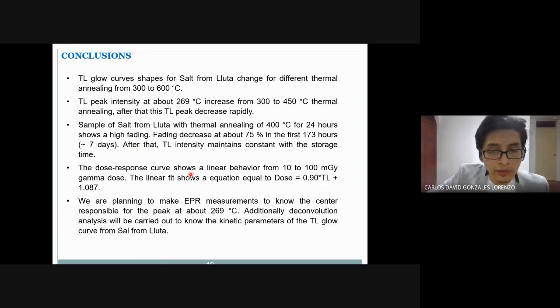The dose response curve shows a linear behavior in this range of gamma dose. The linear fit corresponds to this equation, as you can see here. However, more radiation dose will be necessary to know up to what point the linearity continues. After that, sublinearity or saturation will be reached.